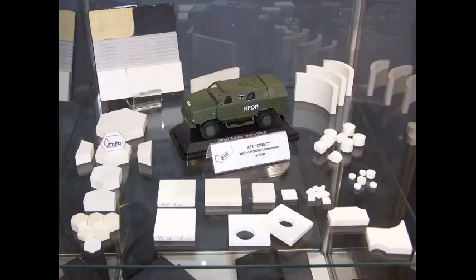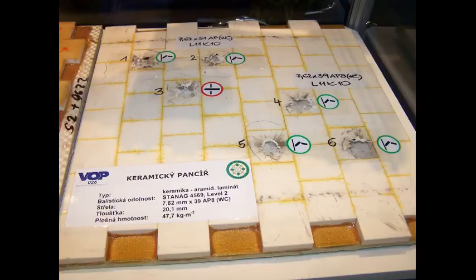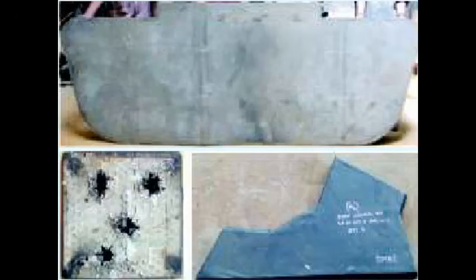In the 1960s, alumina tiles were combined with fiberglass and polymer backing to create protection lighter than comparable steel against certain threats. The hard ceramic face damaged and eroded the projectile. The backing caught fragments and distributed the remaining load. Alumina became widely used because it offered strong ballistic performance at relatively low cost.